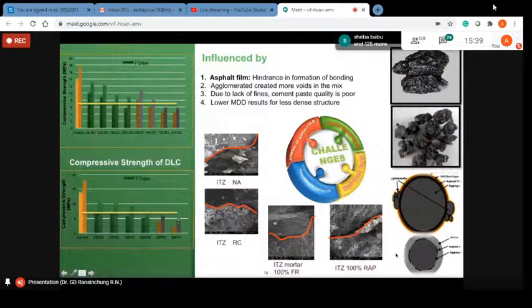From this study, we have learned that water absorption is slightly more, I would say, in the case of RAP materials because of the presence of these contaminants, dust layer, and so on. Whereas if we look at the natural aggregates, it is around 0.7%. And even in terms of aggregate impact value, the coarse RAP material offers a lesser impact value than the natural aggregates. And this again is influenced by the presence of the asphalt film on the aggregates.